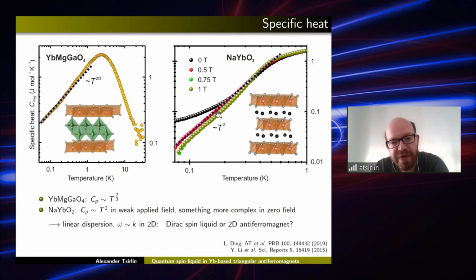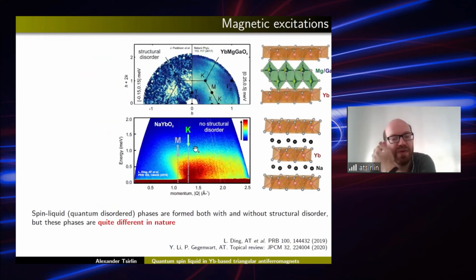Well, of course, you see from the specific heat that there are no phase transitions, so it can't be really the well-ordered, long-range ordered antiferromagnet, but maybe there are just strong 2-dimensional correlations, and they drive the T-squared behavior, but there is no unusual entangled state like a spin liquid. So right now we actually have the possible evidence for both of these interpretations. The evidence for the Dirac spin liquid comes again from the inelastic neutron scattering, where we look at the distribution of the intensity in the reciprocal space.